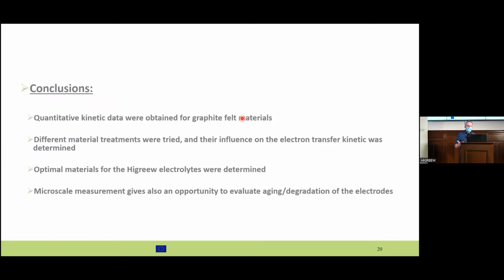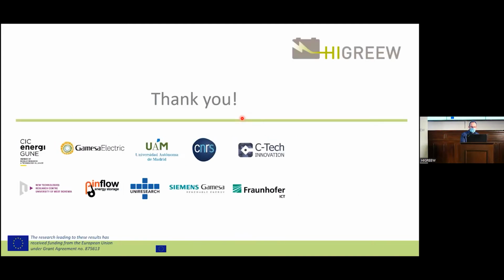And we could identify, especially with urea treatment, some condition where the kinetic of the electron transfer were improved compared to the commercial material. And so the microscale measurement, we think, with the microfiber or with these scanning electrochemical techniques we started to evaluate, could give a good opportunity to evaluate aging degradation of the electrode.